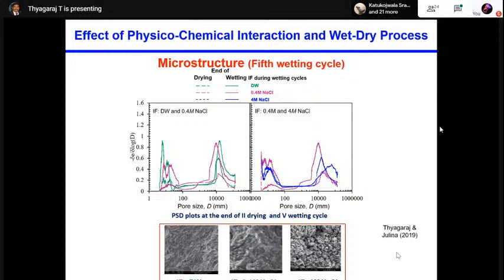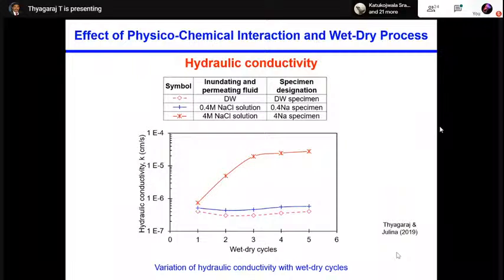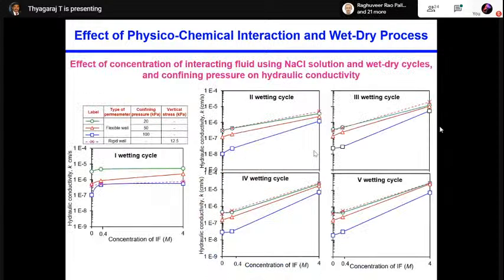There we can see the macro pores in the salt remolded specimens. And further, when we did the hydraulic conductivity, we can see that in case of distilled water, even after repeated wetting and drying cycles, the hydraulic behavior was the same, and with 0.4 molar also, it was 10 power minus 7. Similarly, with the 4 molar, the hydraulic conductivity increased drastically and it became stable around the 4th or 5th cycle. So further, what